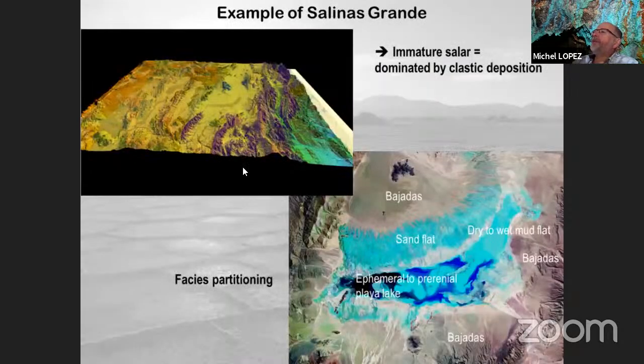So the case of Salinas Grandes is limited by high relief corresponding to the tectonic activity and the progressive subsidence in the central part of the depositional system. The endorheic basin is here, while the Salinas Grandes is located here. You can see with this aerial photograph the sedimentary facies partitioning from the border, controlled by faults, on the two borders. From the border to the central part, you see the bajadas, the alluvial fans, then the salt flat, the dry to wet mud flat, depending on the season, and an ephemeral to perennial playa lake in the central part, where some brine is concentrated.